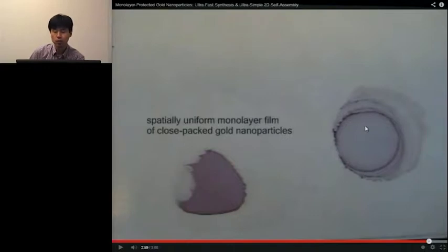When the medium evaporates uncontrollably, most of the nanoparticles get stuck on the outside of the ring, and we call this pattern a coffee stain. In this case, a large portion of the gold nanoparticles is deposited in the outside ring. So we wasted many of the gold nanoparticles on the outside of the ring.